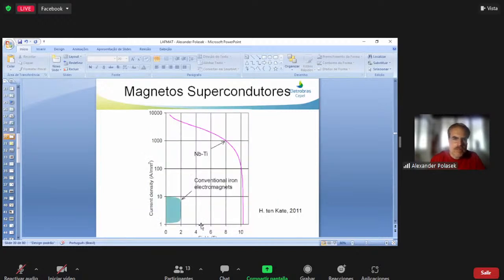And superconductor magnets are the main drivers of applied superconductivity, because for high fields, you generally don't have an option. If you have very high fields, you need superconductors that are typically niobium-based, because with conventional electromagnets, you have high Joule loss, and also you have saturation of the core. The magnet core saturates, and that's why you need superconducting magnets for high field applications.